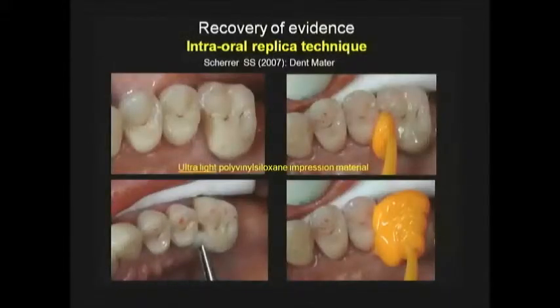Very rarely do we have a whole piece. Very often we only have portions of the crown that broke off. These are called chips. Chips in the veneering ceramic, not exposing the core material underneath, whatever that is. You can secure that information by taking what we call a replica. Please do not use polyether. Polyether does not work with epoxy resin.